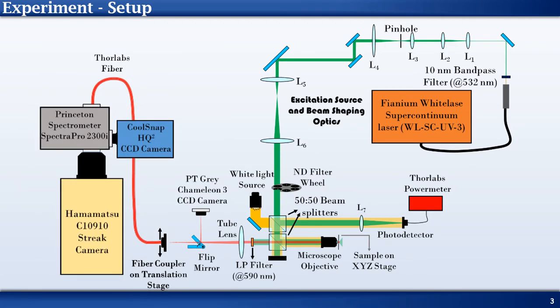Alternatively, we can use a translation stage mounted optical fiber to scan the PL along the radial axis. While performing steady state PL measurements for different positions in this way, we find increased red shift of the spectrum as the distance increases as shown on the graph.